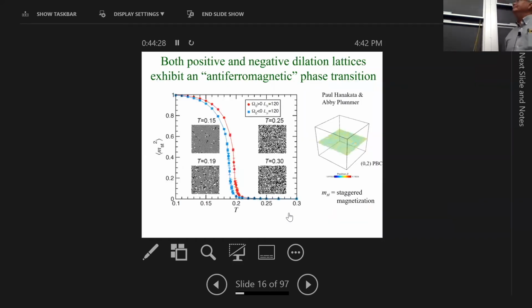So we study this thing, and I'll define it more precisely in a minute. This is a staggered magnetization. Actually, look at the square, it's a little easier to study. And this is an order parameter that's going to tell us what happens when we heat this thing up. You can see at low temperatures, this is temperature measured in units of the bending rigidity, low temperature makes an antiferromagnet with a few defects in it. And then the staggered magnetization, which is a standard order parameter for an antiferromagnet, starts to go crashing down.